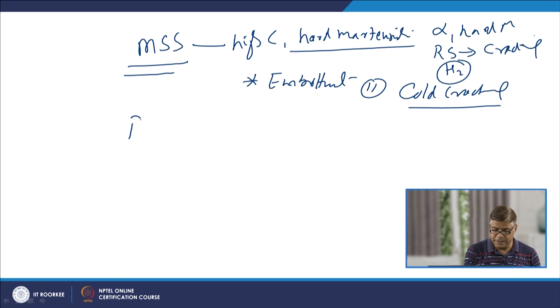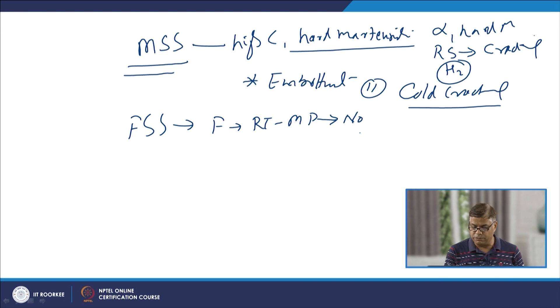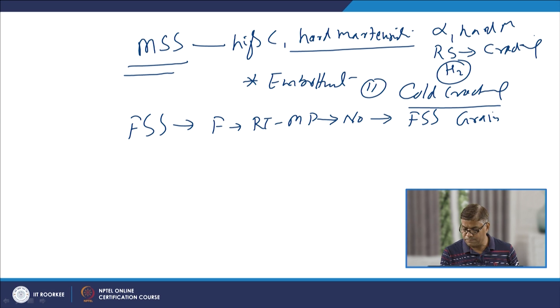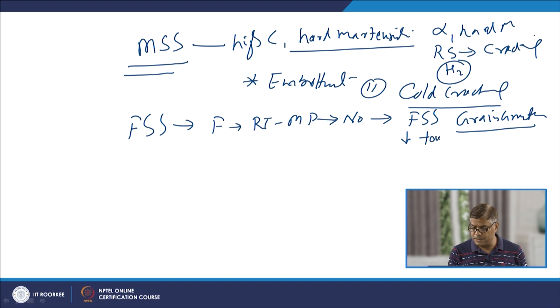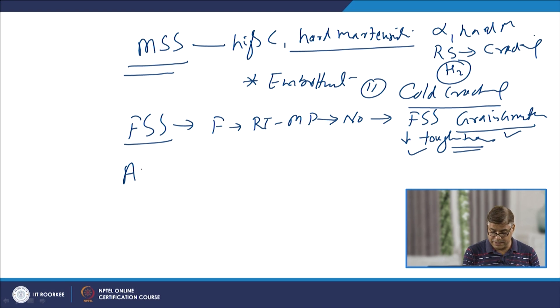Then there are ferritic stainless steels, which remain in a ferritic state on heating from room temperature to the melting point. There is no allotropic behavior, no change of phase, and due to the application of heat, ferritic stainless steels experience significant grain growth in the heat affected zone. Because of this grain growth, toughness of the stainless steel weld joints is badly compromised. So grain size and toughness will primarily determine the weldability of ferritic stainless steel.